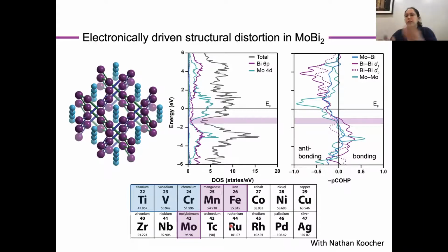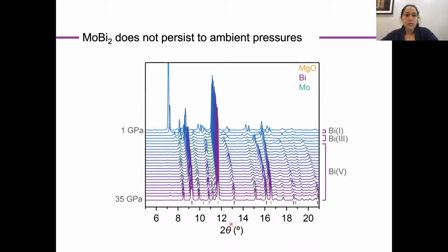But of course, just to shift gears a little bit, that's not the only type of stability we're interested in in the system. It's also important to think about kinetic stability and whether or not we can recover such new phases to ambient conditions. And the short of it is that we can't. Doing the experiment in which we track how this material responds as we decrease pressure in our diamond anvil cells, while we maintain the phase down to about 8 GPa, we no longer see diffraction peaks corresponding to it by the time we get to ambient conditions.